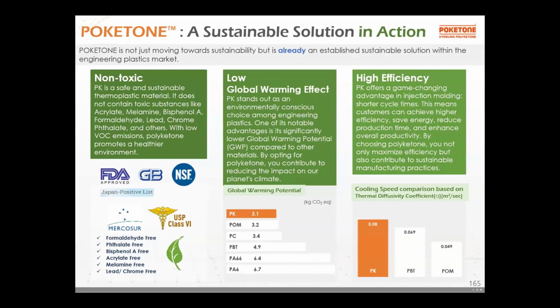And last thing is that we are focusing on the low global warming potential. Current level is around 3.1. It means that 3.1 kg of CO2 is emitted when we make 1 kg of our polyketone. In case of PA66 and PA6, it is 6.4 and 6.7. So it is a very good advantage when you use the polyketone to reduce the global carbon footprint.